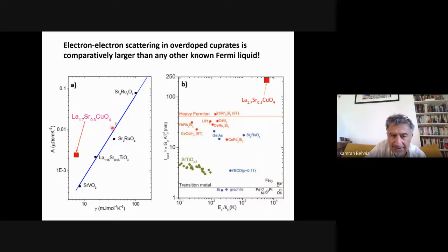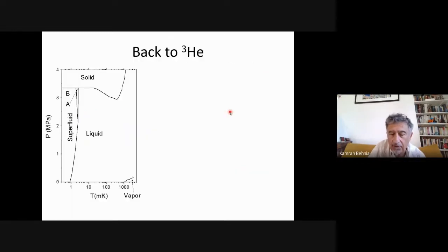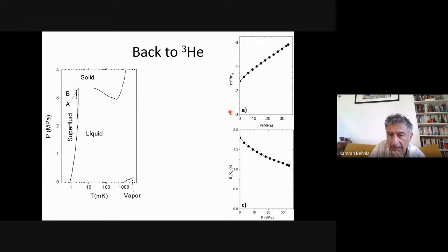Kadowaki-Woods scaling actually works very well for systems which belong to the same family. Here, these are perovskite oxides, and you see that this is not the case of this one. If we use this ratio of T-square resistivity to Fermi energy, all these are in the same range. And actually, again, LSCO, you find something which is not completely unrealistic, but it is even higher than these heavy fermion systems.